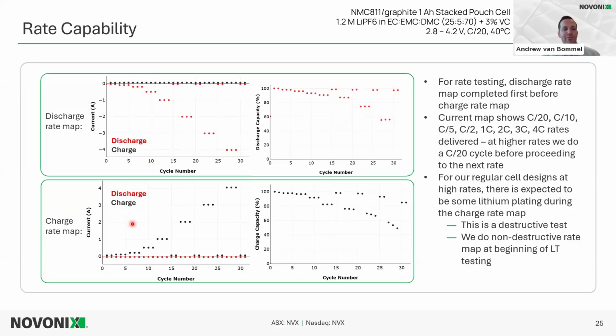So we can do the same for the charge rate map, where the discharge rate stays the same, and then we vary the charge rate. So this is going up all the way to 4C charge. Now, an important thing to see in between these 1C, 2C, 3C, 4C steps, you see that there's loss in capacity in these slower cycles, these C/20 cycles.